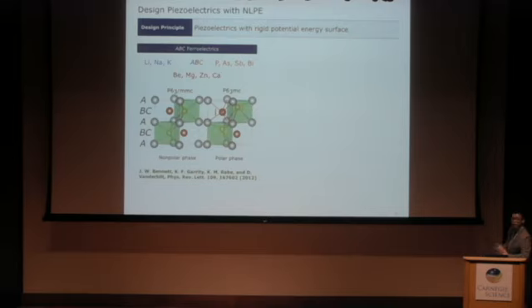I think they talked about this work a couple years ago in this workshop. It is called ABC ferroelectrics. It's a hexagonal crystal, and it is not perovskite. You can really consider this nonpolar phase a layer structure with A, B, C stacking, and the polarization comes from the buckling of these BC layers.